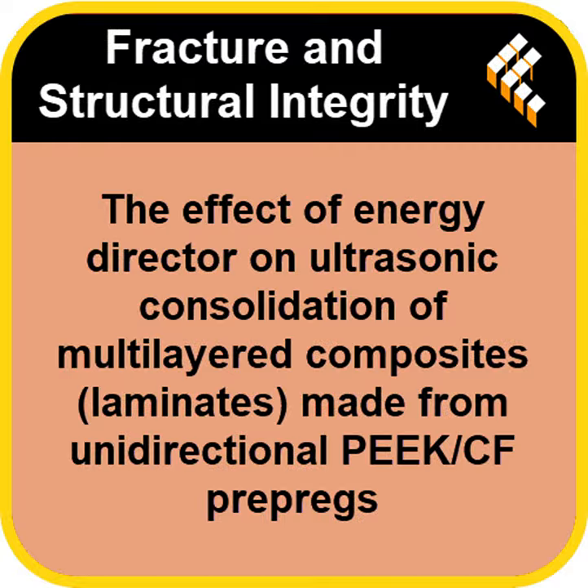Because it melts too well. It's too aggressive. Think of the ED like a layer of hot glue that just melts instantly and spreads out way faster than the stiff prepreg layers can even conform. So it's creating chaos. It creates chaos, it spreads, it gets squeezed out, but in the process, it overpressurizes and physically damages the neighboring prepregs. The ED actually ends up acting as a damper during the initial heating, and then it turns into a destructive force.